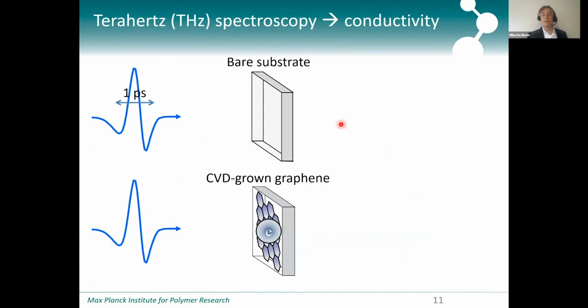And so this is the simplest experiment that one can do with terahertz on graphene. We use what is called CVD grown graphene, so it's chemical vapor deposition grown. You grow the graphene on a copper substrate, then you dissolve the copper afterwards, and you transfer the graphene to a substrate that is typically just glass. So for the simplest experiment, I'm very ashamed that this is really as good as my PowerPoint animations are going to get, so please bear with me.